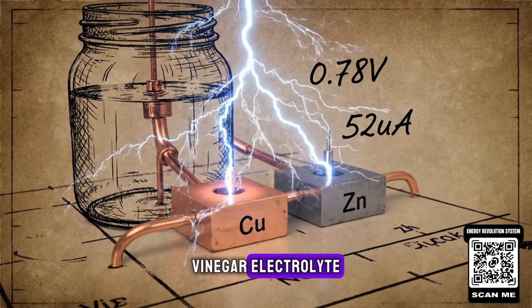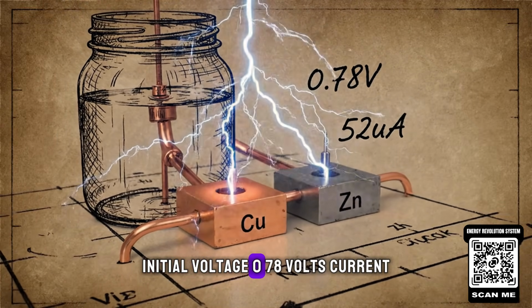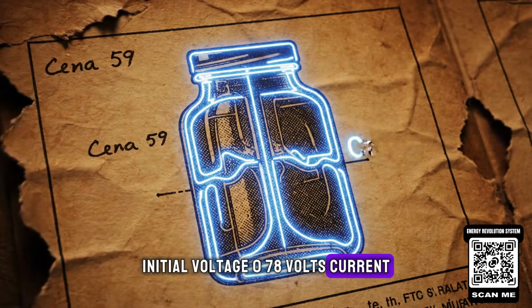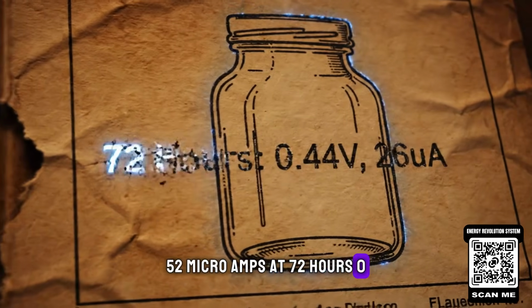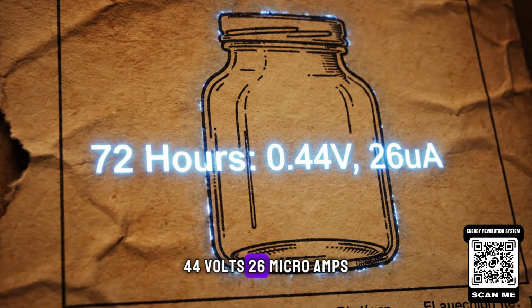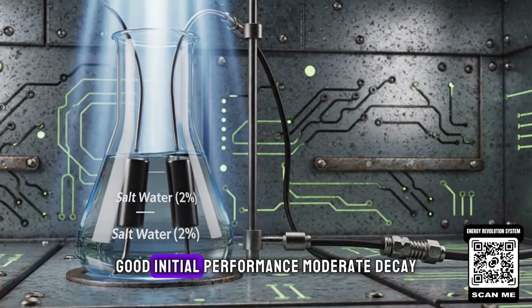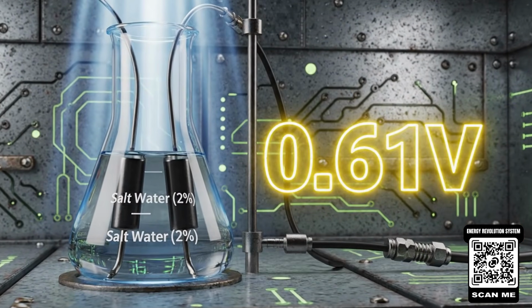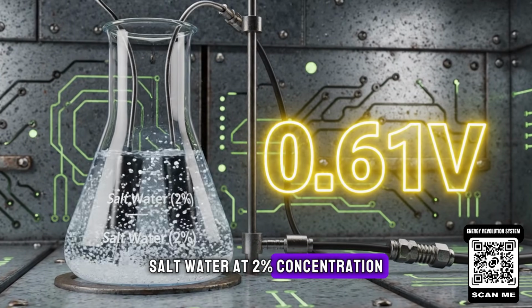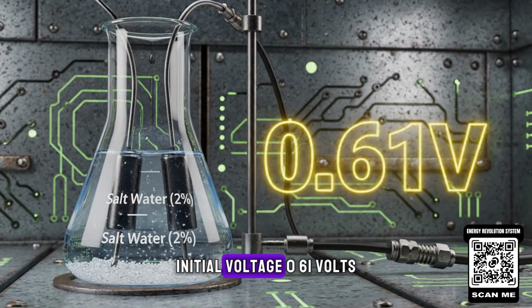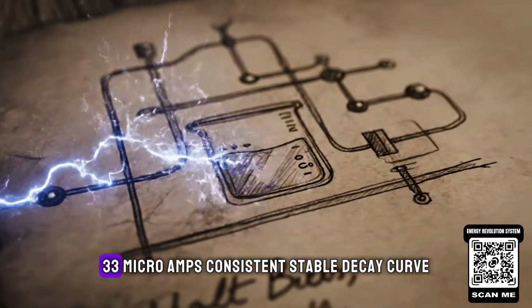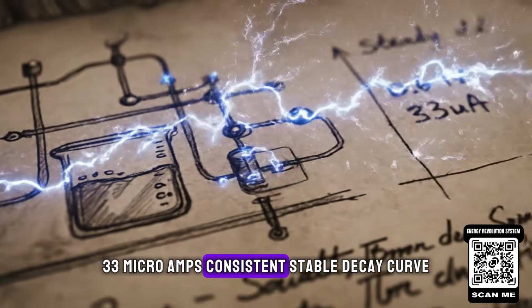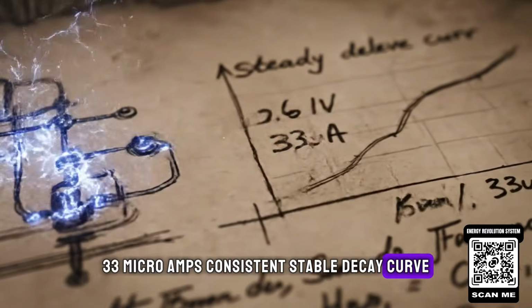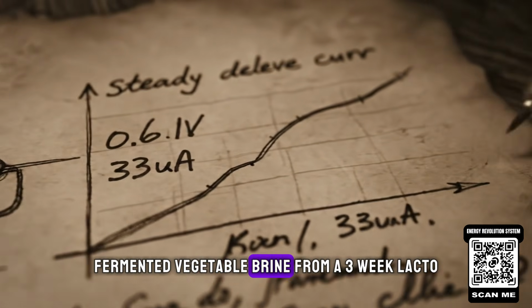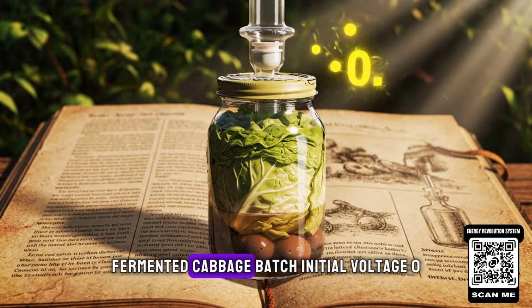Vinegar electrolyte. Initial voltage 0.78 volts. Current 52 microamps. At 72 hours, 0.44 volts, 26 microamps. Good initial performance, moderate decay. Salt water at 2% concentration. Initial voltage 0.61 volts, 33 microamps. Consistent, stable decay curve. Fermented vegetable brine from a 3-week lacto-fermented cabbage batch.